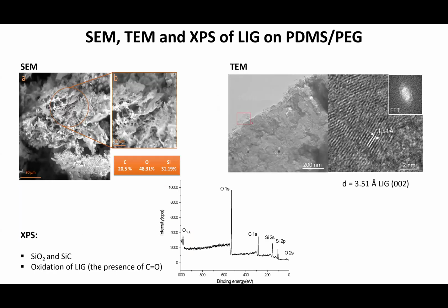Here I show again SEM images. You see this flaky porous structure. It's very interesting, as Spiros said, probably for energy storage, etc. And on the right, we actually performed transmission electron microscopy to confirm that the lattice spacing here corresponds to graphene.